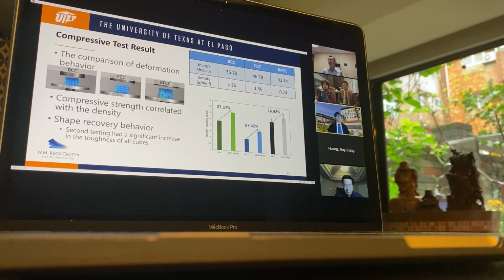In other words, the Young's modulus of the cube is correlated to its density. And after the first testing, we saw that the speed of the recovery was correlated to the shape that we used and not related to the density. So we conducted a second test with the same parameters, discovering that the toughness increased by a different ratio, which is shown in the diagram here.